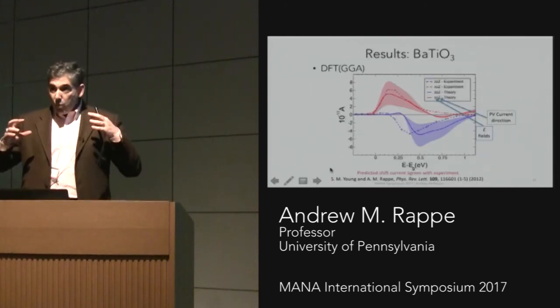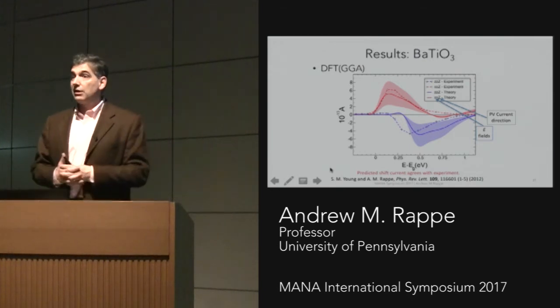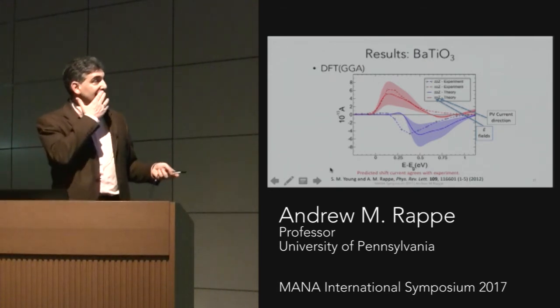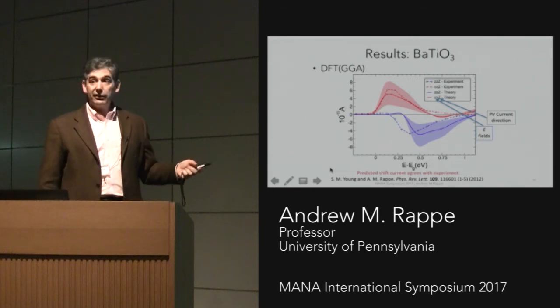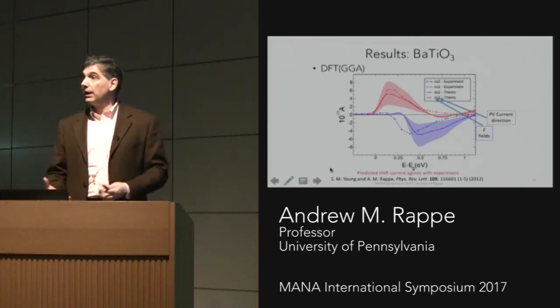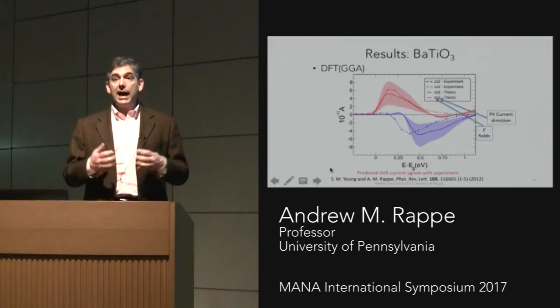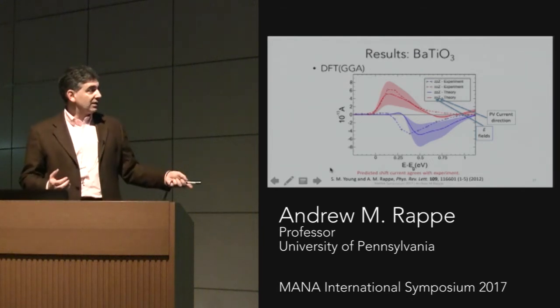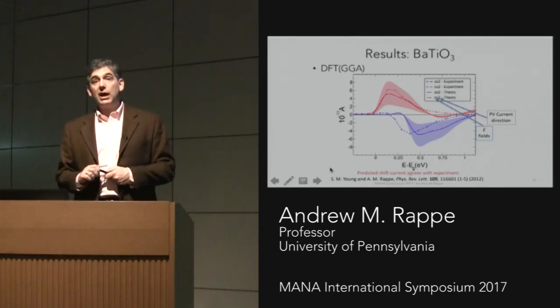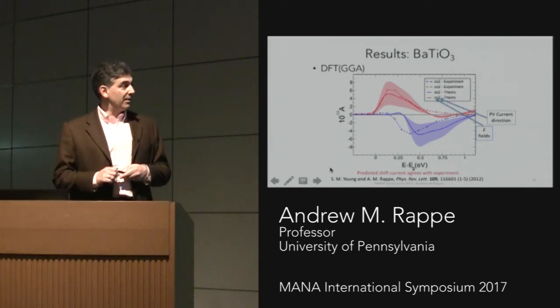But basically, we use this physical formulation to study particular materials, and this is a comparison between the measured current from experiment in the dashed lines and the calculated current in the solid lines, showing that quantitatively we can predict how much bulk photovoltaic current there will be, and this will work out to what there is experimentally. This result by Steve Young was the first time that bulk photovoltaic current was actually calculated and compared with experiment in this way.